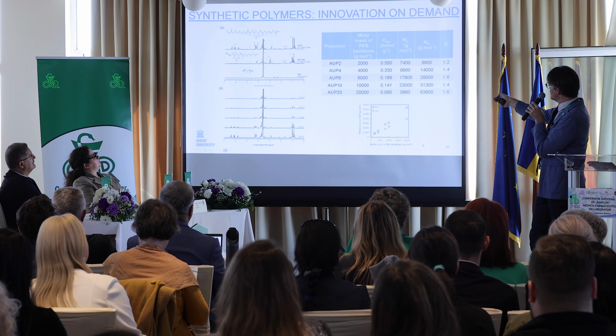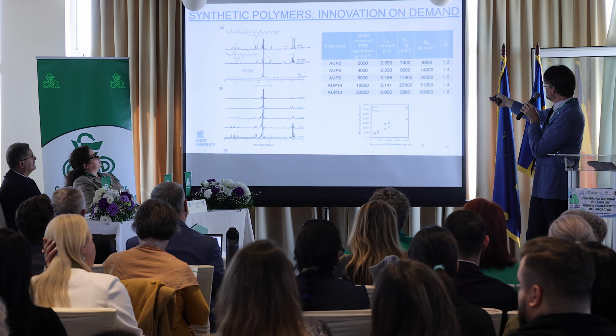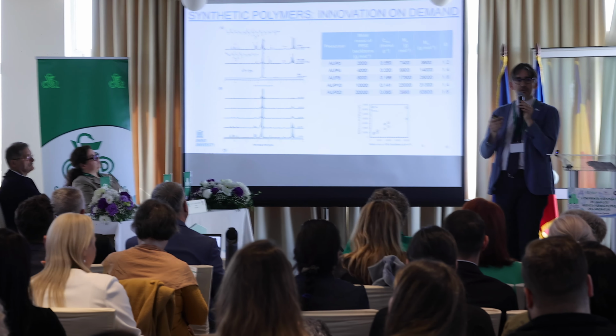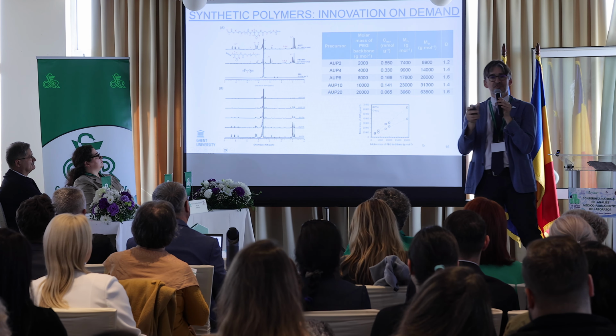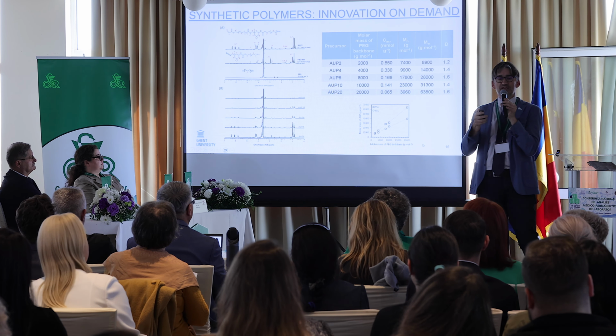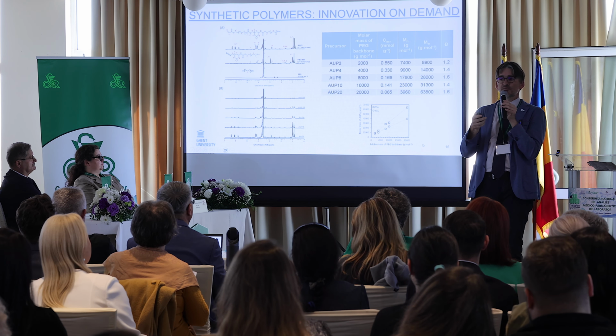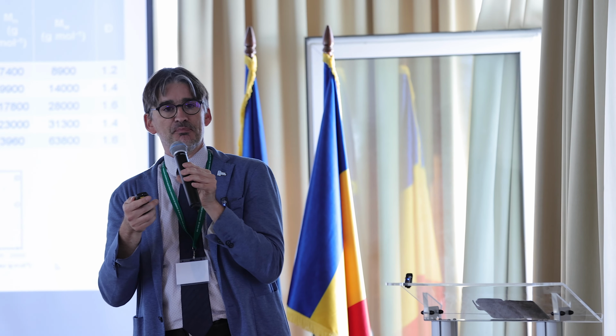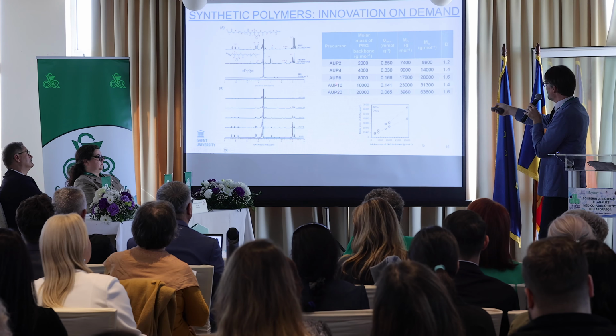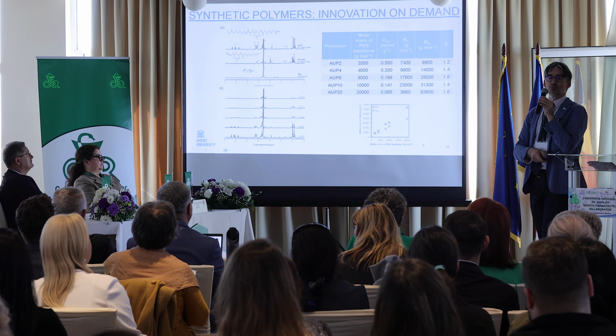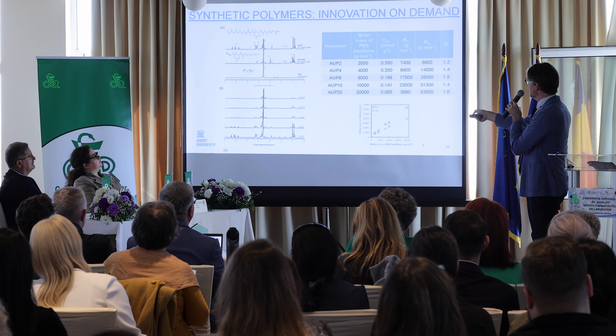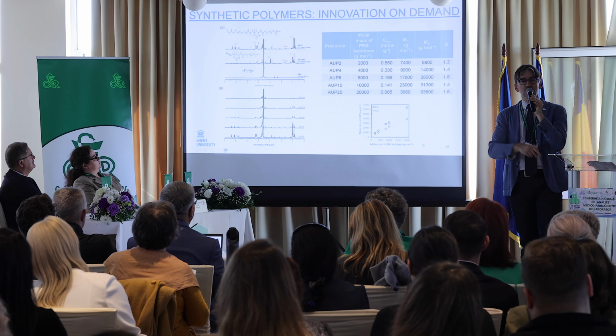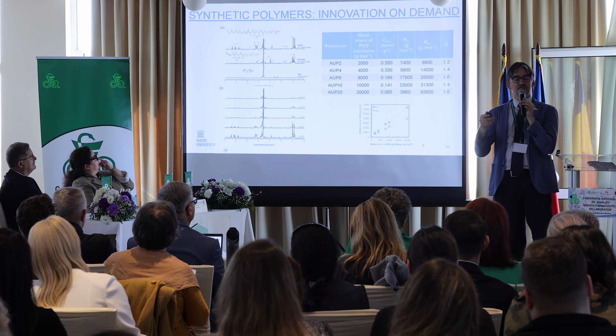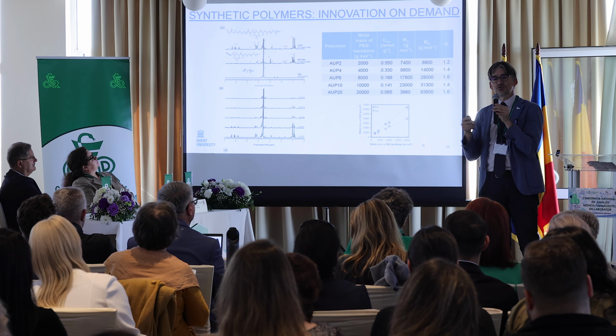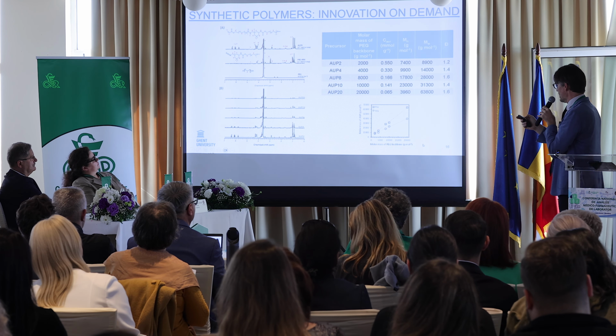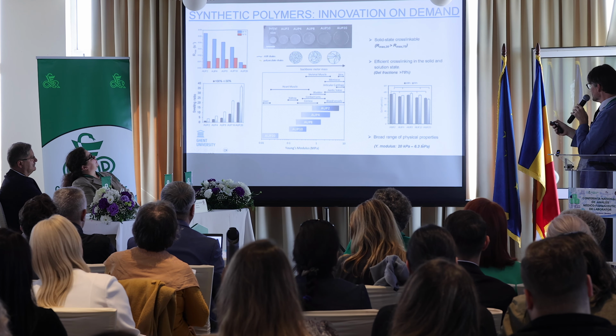So starting from polyethylene oxide, we developed a series of building blocks for hydrogels with different molar masses. So the length of the polyethylene oxide was different, and we anticipated that for biomedical applications, the mechanical properties, but also the release properties of different bioactive compounds could be tuned by varying the exact chemical composition, the molar mass of those compounds. And again, here we characterize the materials in depth through NMR spectroscopy and gel permeation chromatography to really prove that the structure, which I showed you in the previous slide, is the actual one which we are working with.